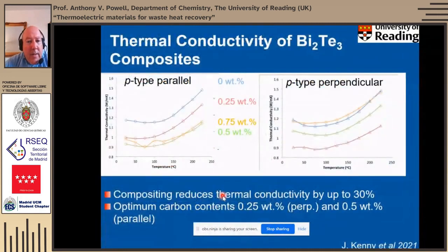And what that achieved is it allows us to have significant reductions in the thermal conductivity. I mentioned the anisotropy of bismuth telluride, so these are measurements made parallel to the pressing direction and perpendicular to the pressing direction. But you can see that in both cases, as we add some reduced graphene oxide into our material, we get quite significant reductions in thermal conductivity, in fact up to about 30%. And we find that the optimum content, for the thermal conductivity at least, depending on which direction we're measuring, is either 0.25 or 0.5 weight%.